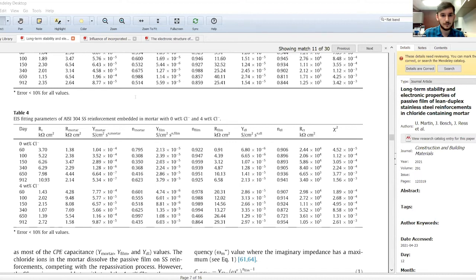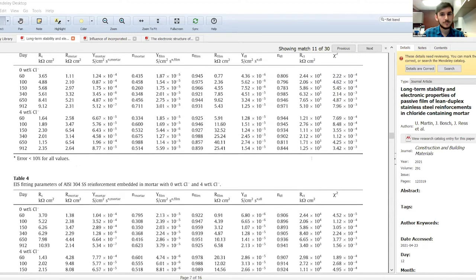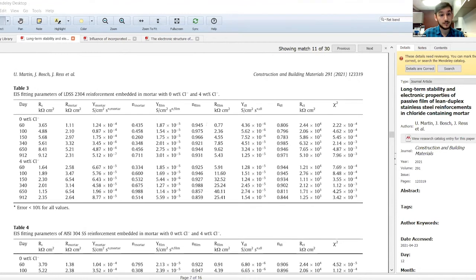Yes, we calculated it, I should have it in here. I didn't present it in the presentation, but these were the fitting parameters of all 3 stainless steels. Here we have the resistance of the film, always in the kilo ohm centimeter square range for the 0 and 4% chloride, as well as the charge transfer resistance, which was 2 to 3 orders of magnitude higher. This order of magnitude was the same for both lean duplex stainless steels as well as the austenitic stainless steel.